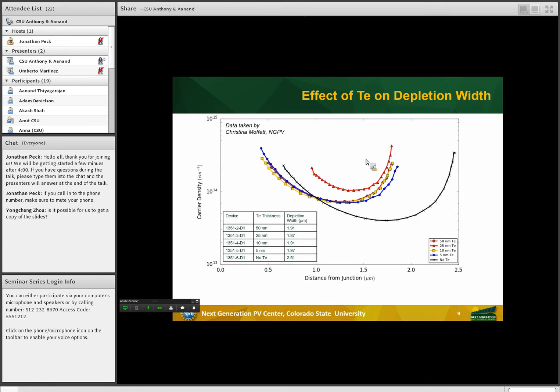More work is in progress in the DFT models, but so far we can see how current DFT results show a valence band pickup at the back of the CdTe layer and how it supports a smaller depletion width as shown in these experimental results. Therefore, a decrease in depletion width is mainly due to how tellurium causes an increase in the hole concentration at the back of the CdTe, as suggested by the DFT results.